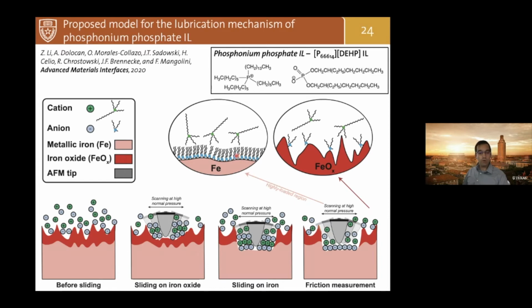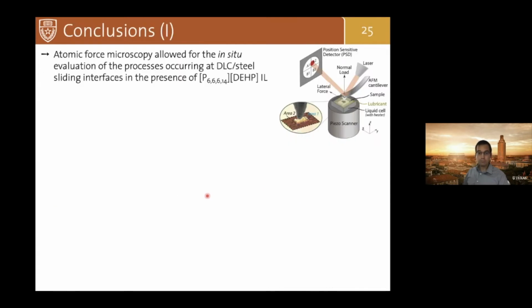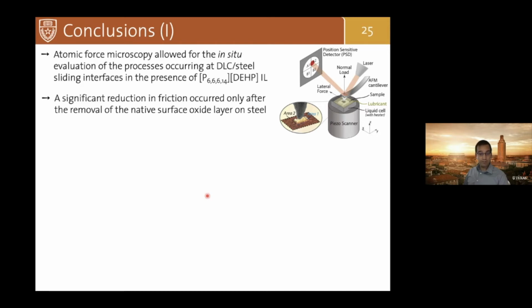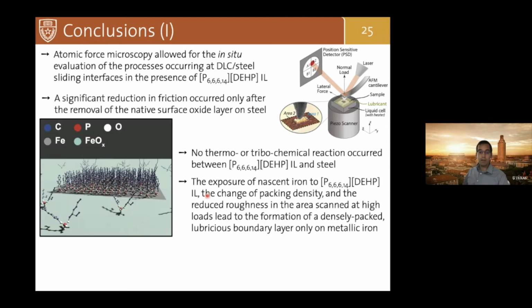So again, in this work, we show how you can combine in situ AFM and advanced spectroscopy to understand the mechanism of action of ionic liquids and how they can lubricate surfaces. So again, atomic force microscopy can be used to evaluate the processes occurring at steel surfaces. I showed that there is a significant reduction in friction after you remove the oxide layer. There is no stress-assisted chemical reaction, so there is no inorganic boundary layer formed here. But we have the formation of a densely packed surface layer made mainly of phosphate ions once you remove the oxide layer. So this work was recently published in Advanced Materials Interfaces. For those of you who are interested, please refer to that. If you don't have access to the journal, please let me know. I will be happy to share the paper with you.